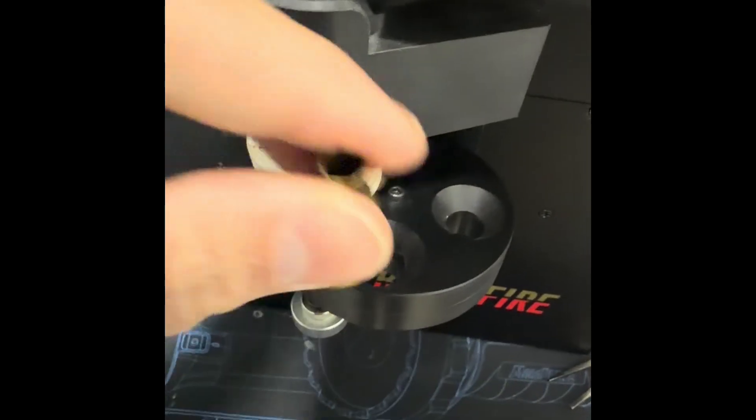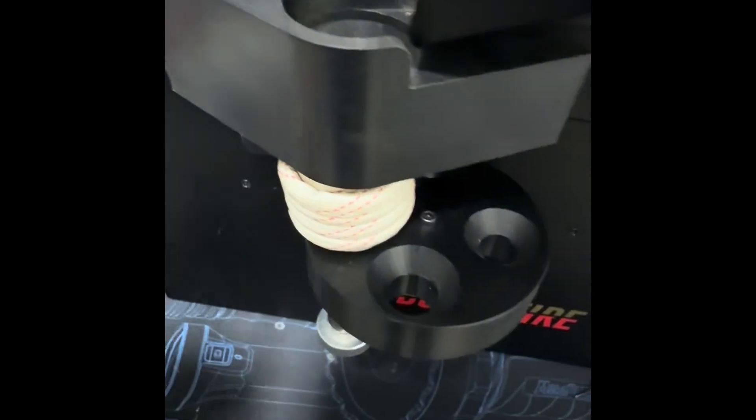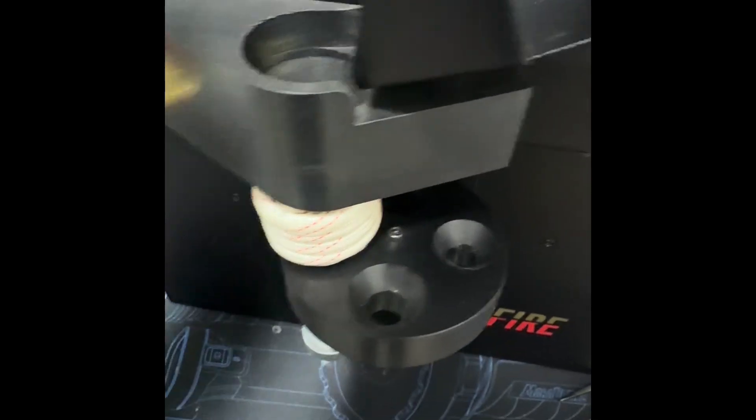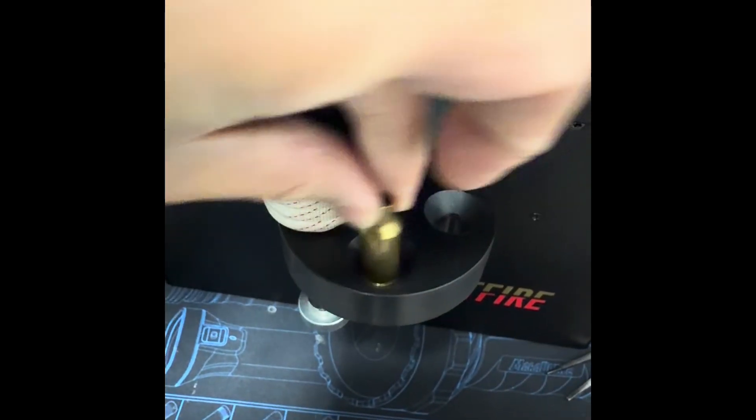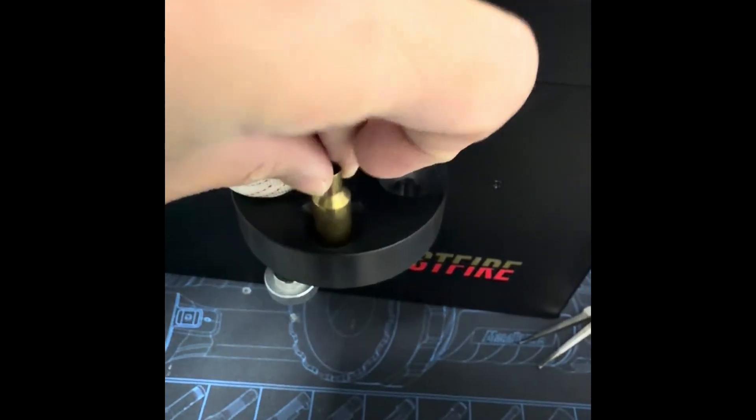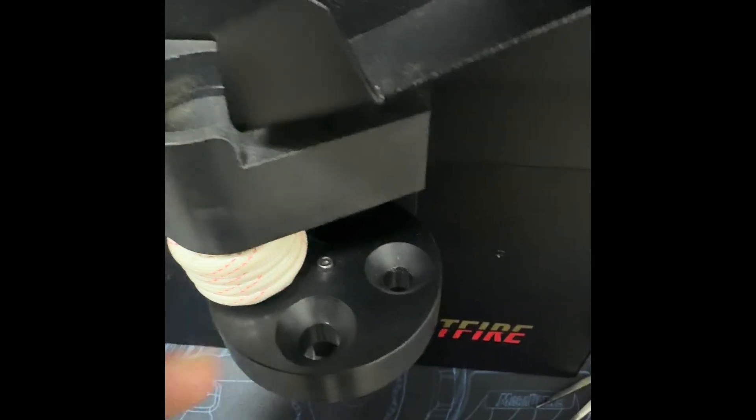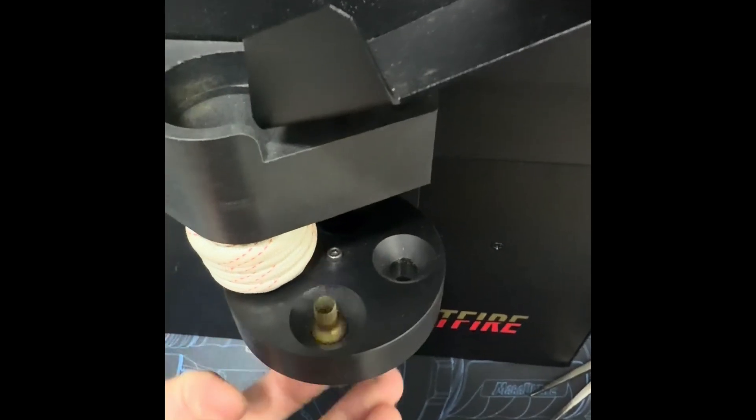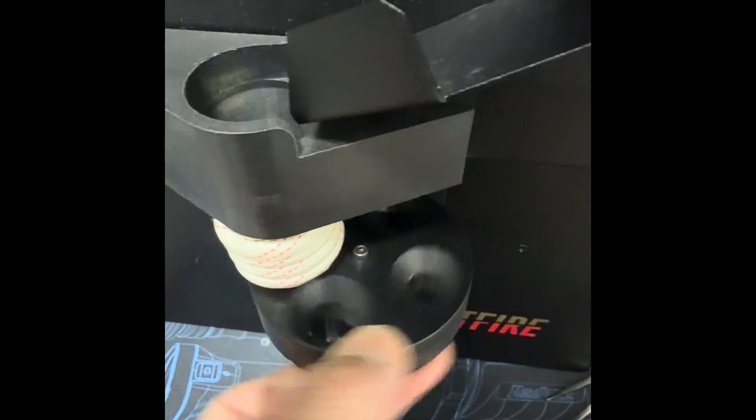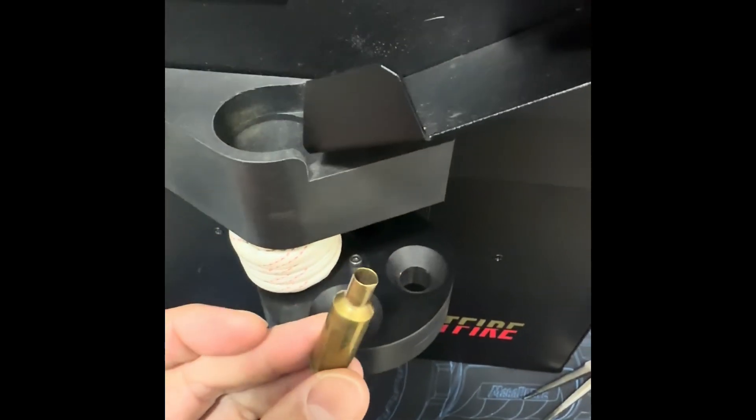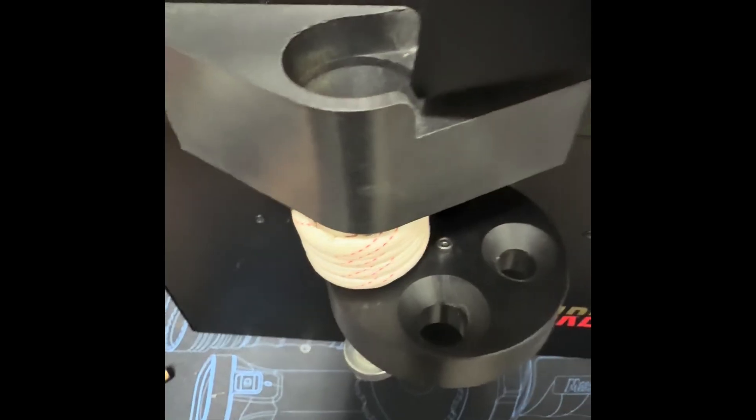Now, another tip is when selecting this hole. I just can't emphasize this enough. Bigger hole, they'll just fall straight in very smoothly. But on a smaller hole that may fit just right, what will happen is as it falls through here, it drops. This case may spin a little and rattle its way in. That will delay the time that it gets annealed and you make it uneven anneal. So make sure you pick select the right hole. Not too big, not too small. The one in the middle, right? Give it some room. Make sure it falls straight through. It's not leaning heavily towards one way. And that's the correct one.